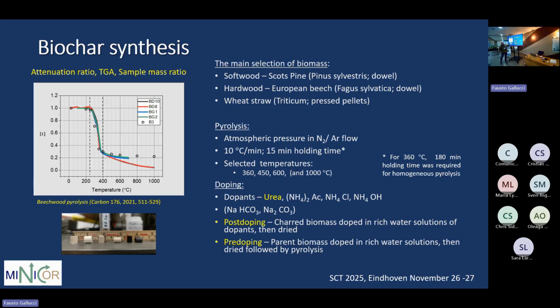We work under atmospheric pressure conditions using nitrogen or argon. We use a temperature ramp and a holding time to wait out the pyrolysis. For lower temperatures, in particular around 360, you have to increase the holding time because the chemistry is much slower. The dopants we chose are nitrogen dopants, and the principal one is urea because it is strongly connected to manure and natural sources of nitrogen, and it is a pure chemical compound. Other ones that we don't describe here are sodium-based carbonates.